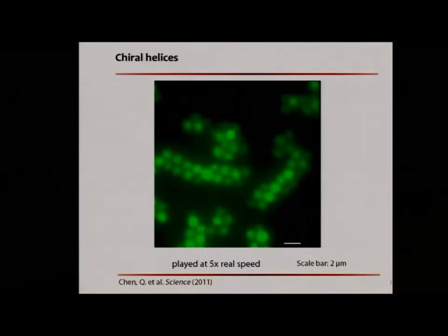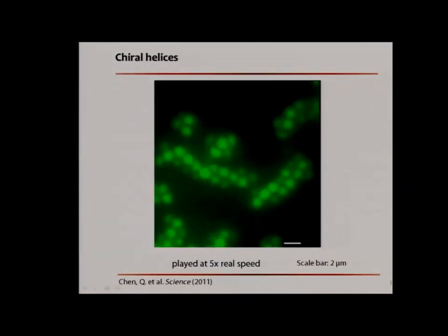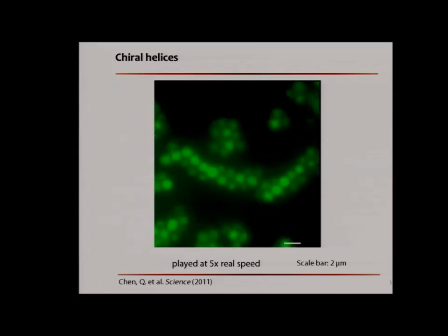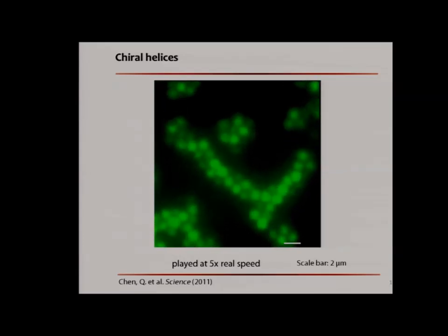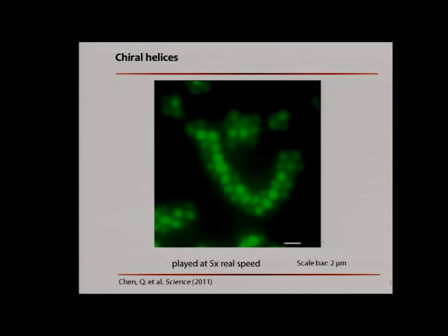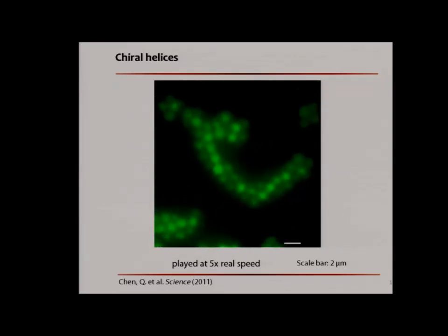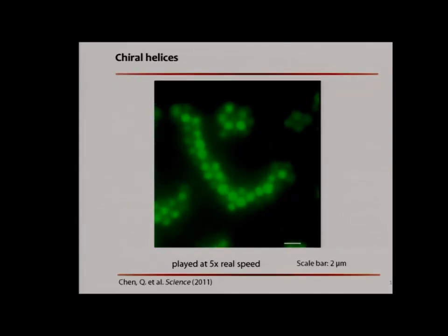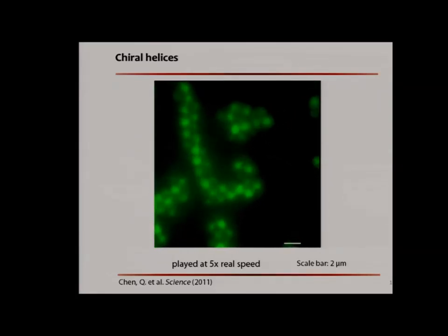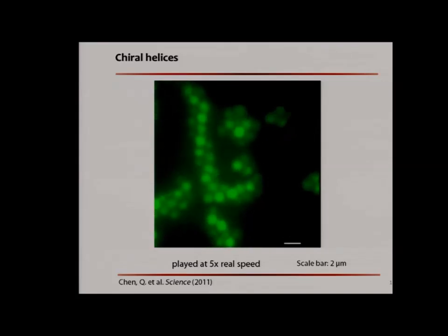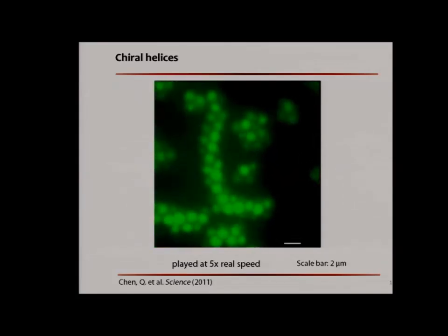As you can see from this movie, we have 2 helical chains of different handedness. And that is because helical chains with different handedness have the same free energy levels. Those 2 helical chains are trying to hold hands with each other, and once they're hand in hand, they start to relax. In this particular case, they're holding hands through the kink, and the kink can eventually get annealed out due to the thermal fluctuation of the particles.